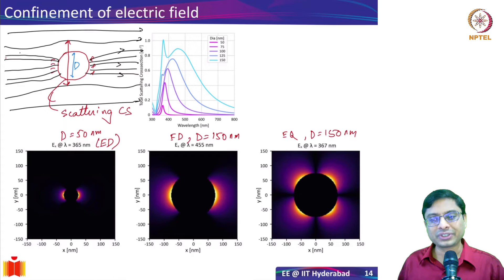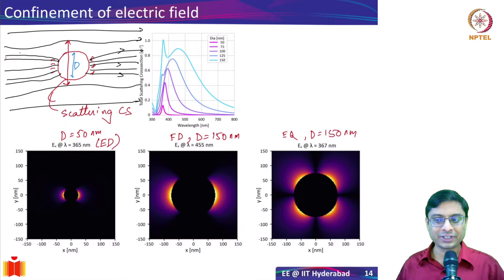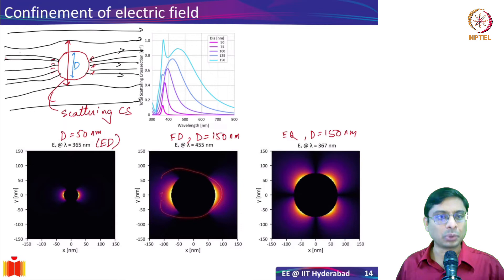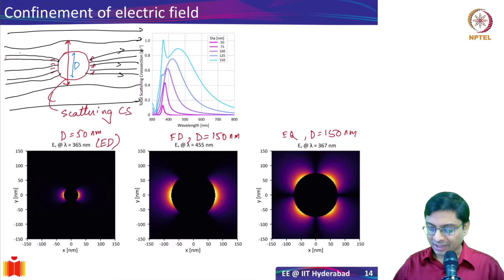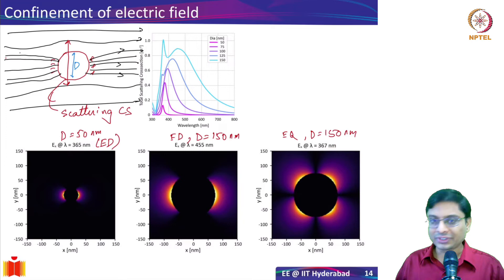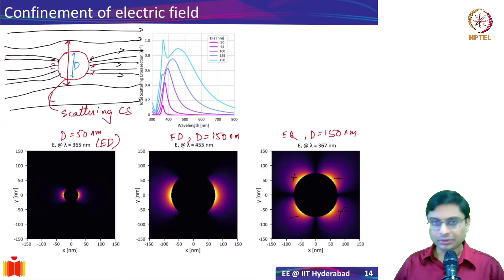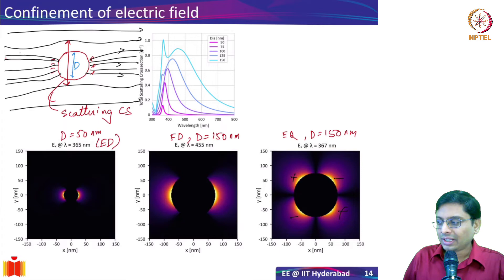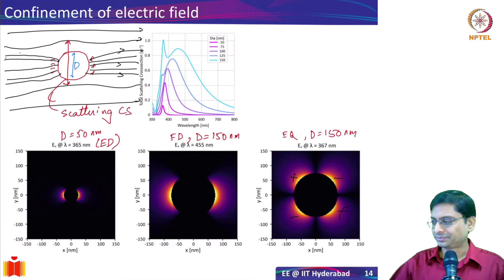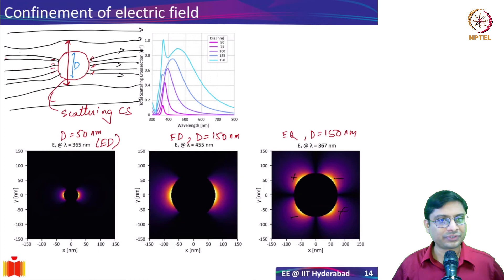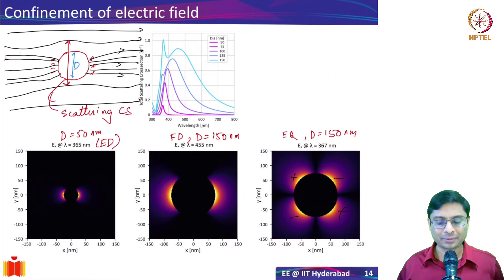As you increase the size, the dipolar field profile is maintained. At 150 nanometer diameter, at around 455 nanometers the field still looks like a dipole. But at 367 nanometers for the 150 nanometer particle, there is an additional peak — the quadrupole mode — because instead of plus and minus, you now have plus, minus, minus, plus: four charges effectively. You can also have higher-order modes: octupole and so on, where the field intensity distributions become more complicated. As size increases, the resonance red-shifts, the field exhibits dipolar behavior, and larger particles develop these higher-order modes.